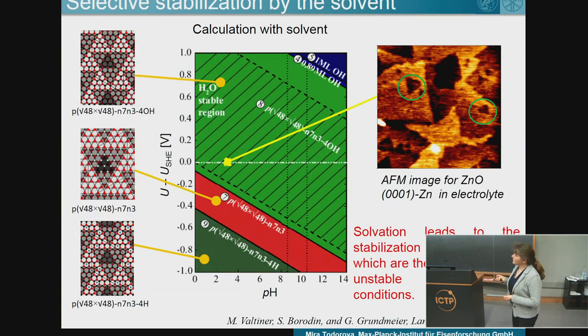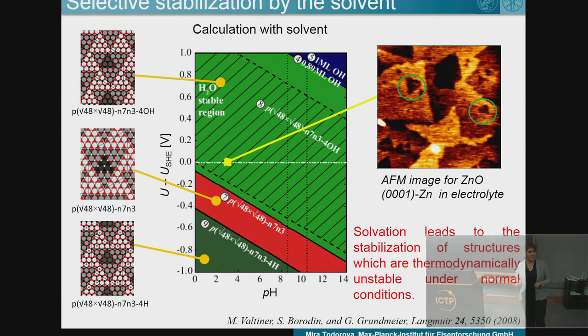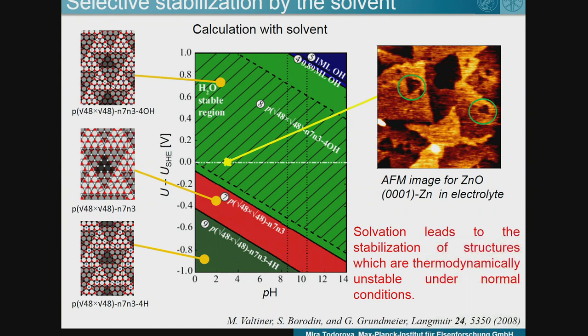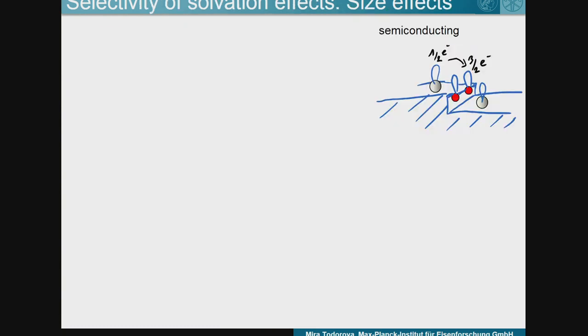When we look at the surfaces in which we considered now the solvent, we do see that the diagram changes. So these greenish and red colors are triangular reconstructions, either with OH group, with hydrogen groups, or without any coverage. And what we can see is that now in the region where the experiment sees triangular reconstructions at the surface, we can also see within our phase diagram a triangular reconstruction at the surface. So obviously, solvation effects are important, but can we understand what they actually do? What's the underlying physics? And for this, we need to take a little bit closer look at the structure.